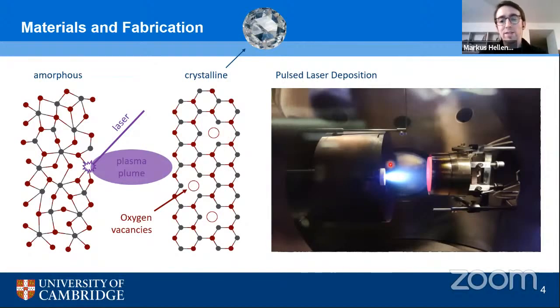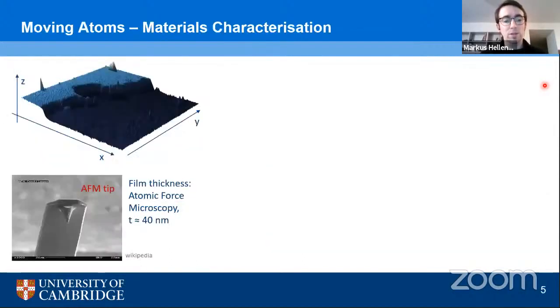So before making any devices out of this, however, we want to make sure that we actually have the crystal structure and the materials that we want to use. For this, we have some different techniques at our disposal. So just point them out briefly to give you an idea. So we can use atomic force microscopy to measure the roughness of our materials and the thickness. In this case, we measured a thickness of about 40 nanometers, so everything is very small.